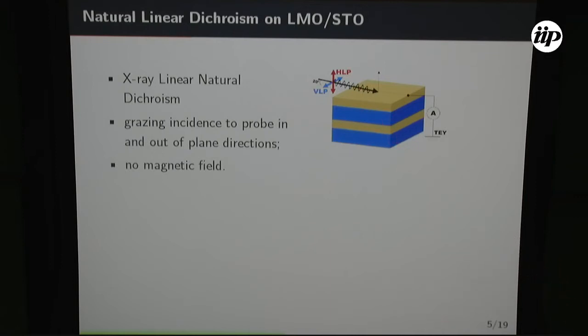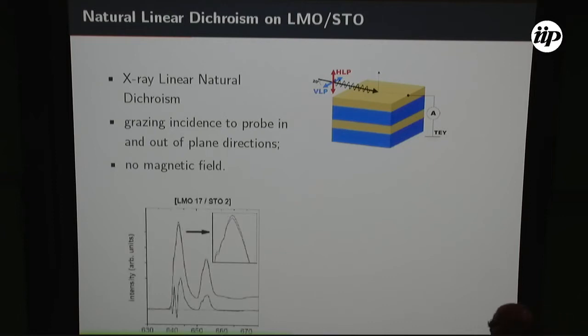So we say that the X-rays have a searchlight behavior. You see things like that when you have the polarization vertical, or like that when you have the polarization horizontal. And the idea is to probe the difference between the chemical bond perpendicular to the plane and in the plane. Results. So here is the measurement for a sample that has the thickest manganite layer.